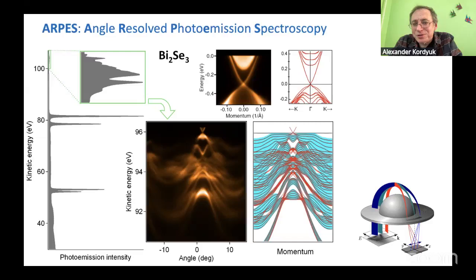No, I understand topological protection. For me, I understand it in two ways. One way is how I observe it, because what it means is that in experiment the bands disappear. This does not mean that they should disappear from calculations. That means that they became so wide and so low in intensity that we can't see them, when the scattering increases. If you introduce some dirt on the surface, the forward scattering, the unitary scattering, increases. It means that quasi-particles at this level just scatter, the lifetime reduces essentially, and you could not see this band. But this does not happen with topological states, because the phase space where an electron could scatter is much smaller, because there are different spins